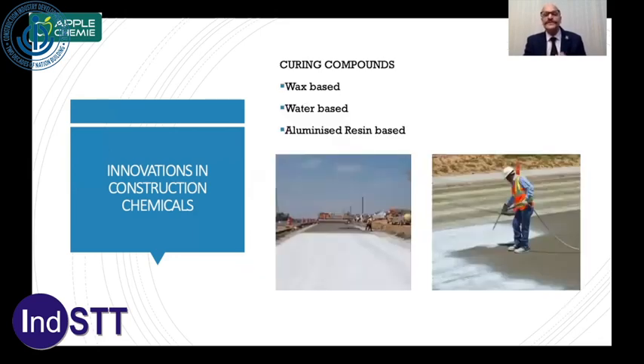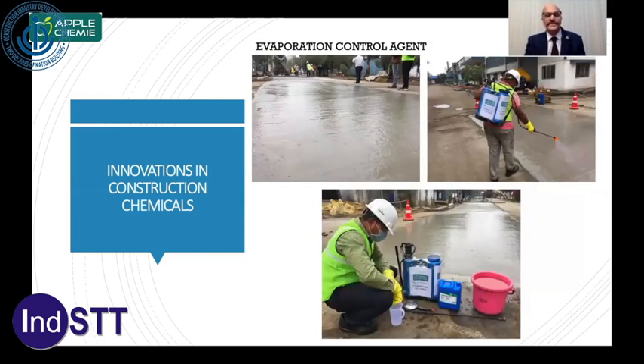Similarly, there are innovations in the other products on the construction side, which is curing compounds. Curing compounds have changed the huge amount of water. The water which we are using can be reduced to a very, very large extent. They are of wax base, water base, or aluminized resin base. And once you put a curing compound, then the evaporation losses are controlled, there can be good protection, and water for the curing can be totally saved.